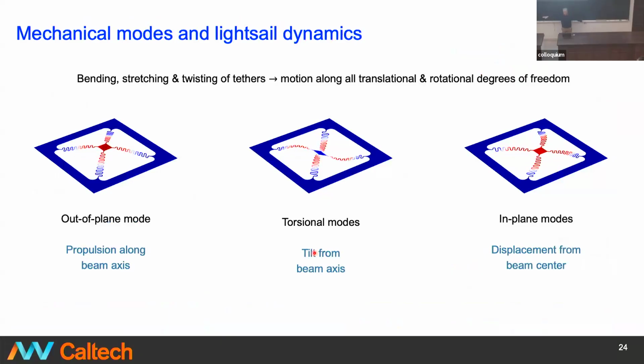So we have a thin membrane, and we're propelling it along an optical axis. The membrane itself is not a rigid structure. If it's large, it has its own modes. In our laboratory, this is our E. coli, or our mouse vector, so to speak, for optomechanics. It's a thin light sail membrane that's held on ligaments that are highly compliant, and they're attached to a rigid silicon frame. And that allows us to measure the dynamics and then track this easily in the lab.